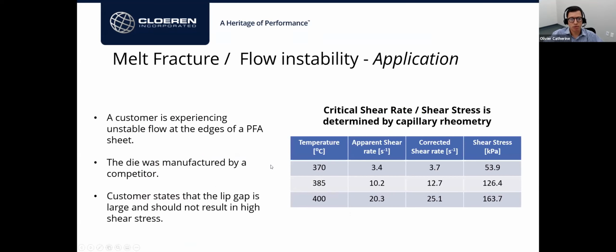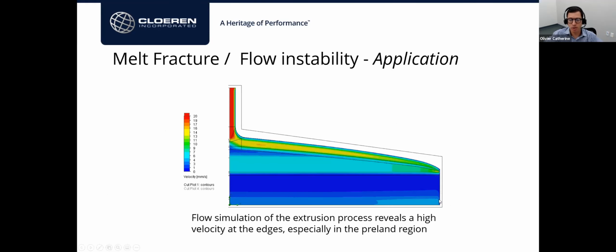So I wanted to show an actual example of a customer who was extruding PFA with a competitor's die, and we're having some flow instability at the edges. And this customer is actually making a sheet and has a fairly large lip gap. So when I measured the PFA, I found that the shear rates at which the flow became unstable was extremely low, right? So we had a very narrow processing window with those materials. But indeed, the sheet die that they use has a huge gap.